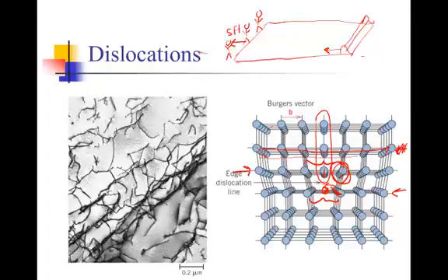And it turns out this is what allows metals to have malleable properties, to be ductile materials, and this motion doesn't happen in ceramic materials, for example, even though the dislocations are there, because for reasons we'll go into in the future, the dislocations aren't allowed to move through ceramic crystals, and that's why ceramics tend to be very hard and brittle.